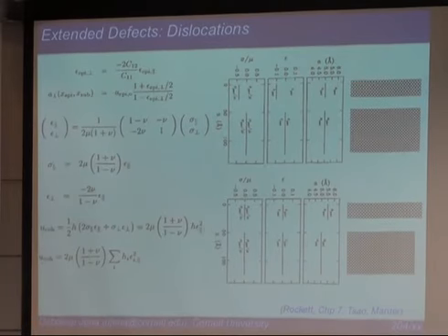And similarly, stress in the parallel direction is, whatever it is, because you know the strain, you can always find the stress now. They're related through these matrices. You'll find it goes negative. Very importantly, for this situation, the stress in the perpendicular direction is 0. Why? Because it's free. Right? So this is all the details of all the terms, in pictures what we just said. Is that clear? Yeah. And once you know that, all the energies are basically areas under the curve, and squares. Energies are essentially just that, once you've found what your epsilons and stresses are.